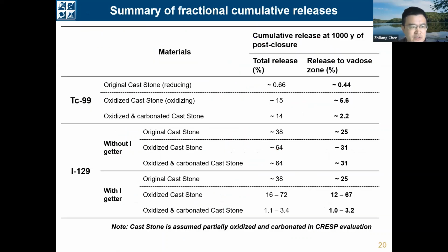And here I summarize the release of the technetium and iodine for different cases. For the technetium, you can see that the release from the original Cast Stone is lower, less than 1%, but oxidation and carbonation increase the release by a lot. And for the iodine in the system without the getter, the release is much higher compared to the technetium. And also you can see that oxidation and carbonation will further increase the release rate. But for the iodine in the system with getter, we will notice, like the results at the bottom, the oxidation and the carbonation is actually beneficial for the iodine stabilization, and that can reduce the release rate by a lot. This is because the oxidation and carbonation of the Cast Stone will change the redox state of the Cast Stone to be beneficial for iodine stabilization, and this result is consistent with our previous observation from the predominance diagram.